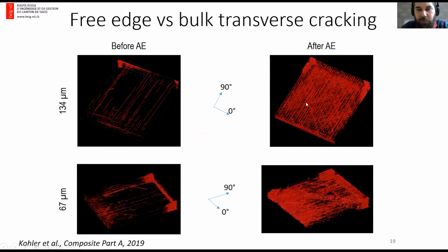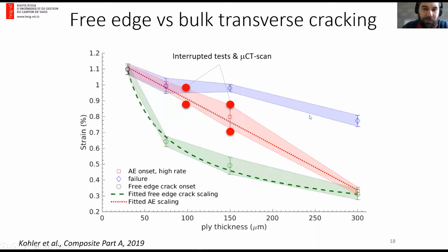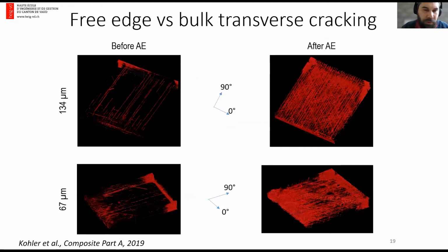While just after the onset of acoustic emission, the composite is full of transverse cracks and also some cracks in the 45-degree plies. So you can see here that the onset of free edge delamination corresponds to very small cracks that don't go in depth. Onset of acoustic emission really corresponds to what happens in the bulk of the material.